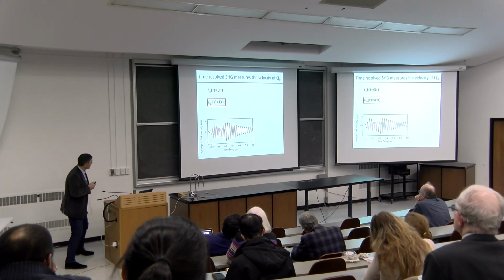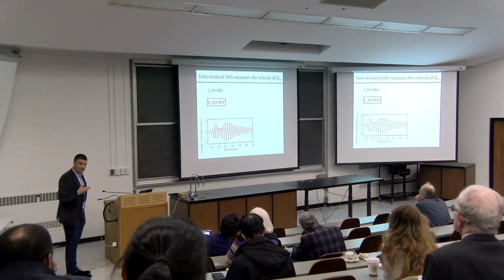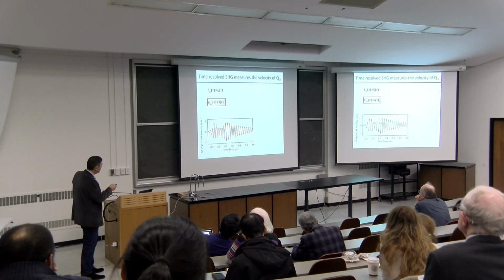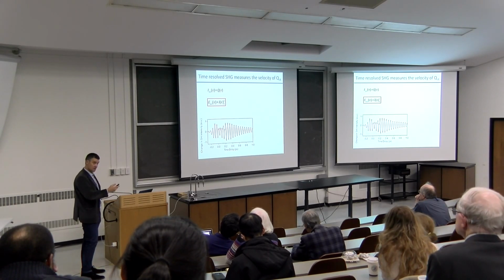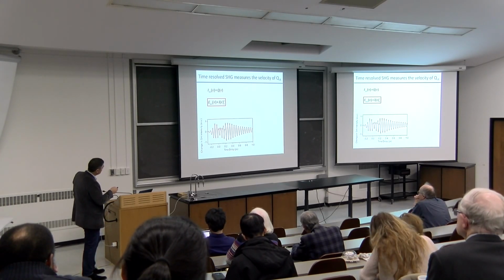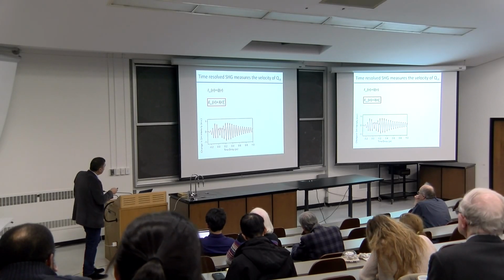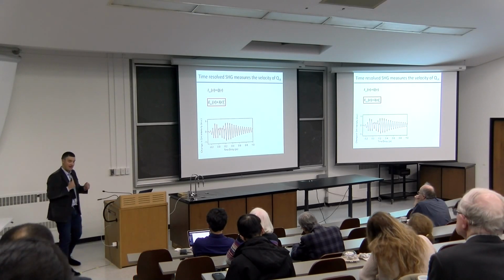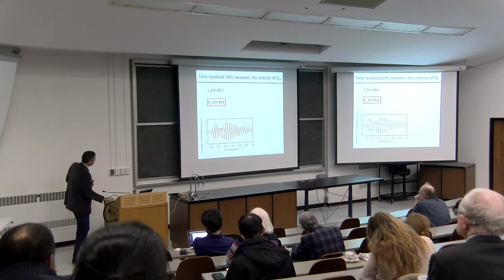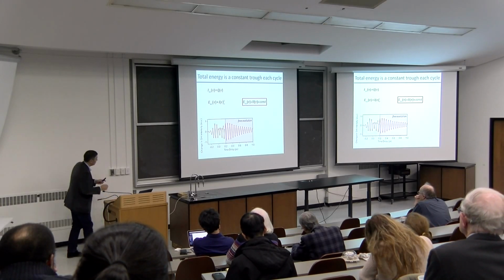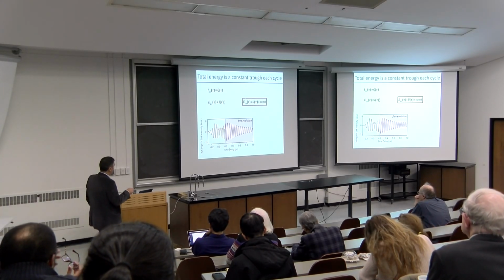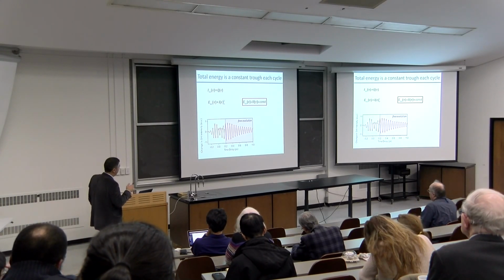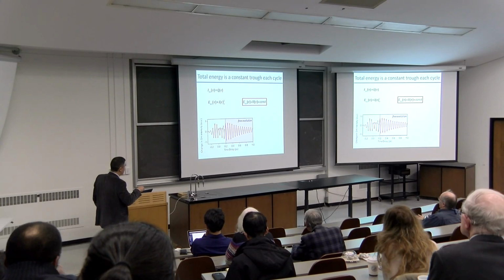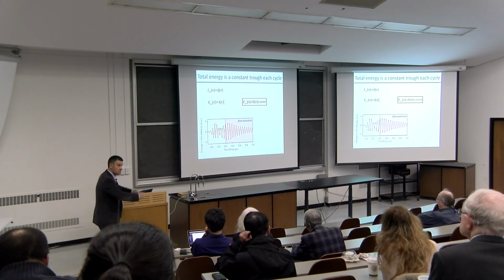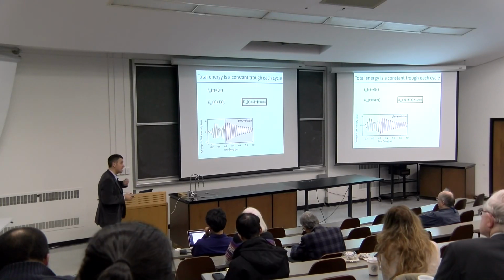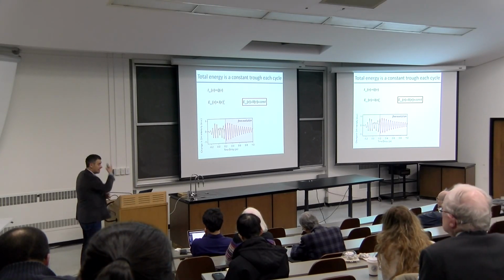the following reason. So as I told you, we are measuring a signal as a function of time that is proportional to the velocity of the mode, which means that now, modulo a constant that I don't know, I have a measure of the kinetic energy of my mode, okay? So let's see. Then what I'm going to do is wait until the pulse is gone, because of course here I was pumping the system, I was putting work into the system, and so the phonon was being accelerated. When I stop driving it, then I have an oscillator that is going backwards and forwards.